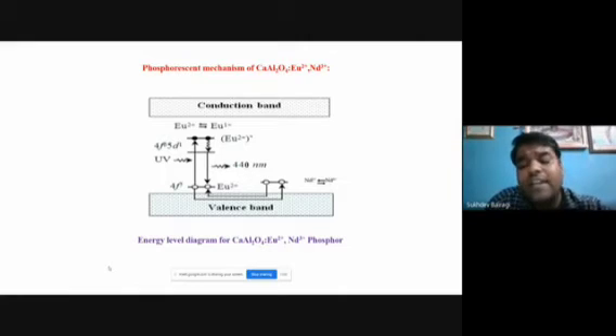The secondary ion acts as a trap of the hole and lies between the excited state and the ground state of the europium ion. When the exciting source is cut off, some of the holes are captured by the secondary ion, and the traps are thermally released very slowly to the excited state of the europium ion. Finally, returning to the ground state of europium is accompanied by the emission of light. The mechanism of the long persistence is due to the hole trap-transport process. When we further increase the secondary ion concentration, the emission intensity goes down. The reason seems to be that the concentration of the second rare earth ion has an optimum value, and more produces more crystal defects apart from the traps.